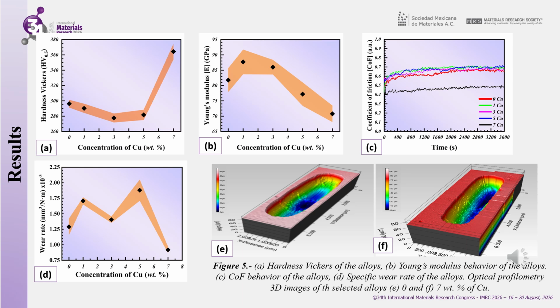Figures 5e and 5f illustrate the three-dimensional images obtained by optical profilometry of the worn surfaces of the alloys containing 0 and 7% by weight of copper, respectively. Both images reveal a clearly defined longitudinal wear pattern accompanied by topographical variations represented by a color-coded height scale. The determination of the volume lost was based on the images obtained, with the objective being to establish specific wear rate values for each of the alloys.